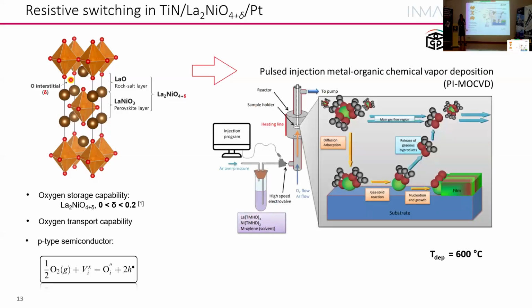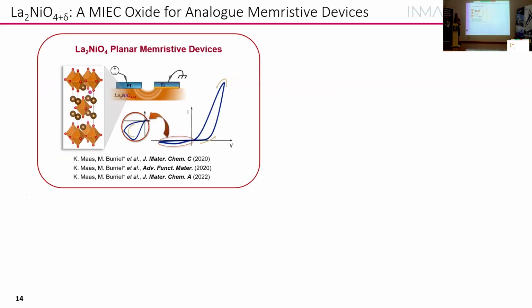So we did it in Grenoble, in the lab where I used to work, LMGP, and we were using pulsed injection metal-organic chemical vapor deposition. So we mix the precursors in a solution. We evaporate them by flash evaporation with an injection valve to the evaporation zone. They're carried by a gas flow, and they go to the reaction zone where they are deposited, and we have the film growth.